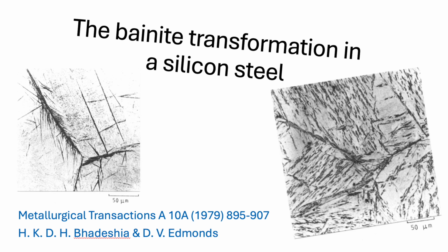And there was more. The chemistry itself argued against it. Silicon, the main alloy here besides manganese, actually increases the activity of carbon. It should make carbon want to move more easily, not less. So if solute drag, particularly involving carbon, was the main control, you wouldn't expect such a strong slowdown, such a pronounced B temperature bay. Exactly. You'd expect the bay to be weakened, maybe disappear entirely, with that much silicon boosting carbon activity. But it was strong. It pointed towards a mechanism that wasn't primarily controlled by simple diffusion or solute drag.